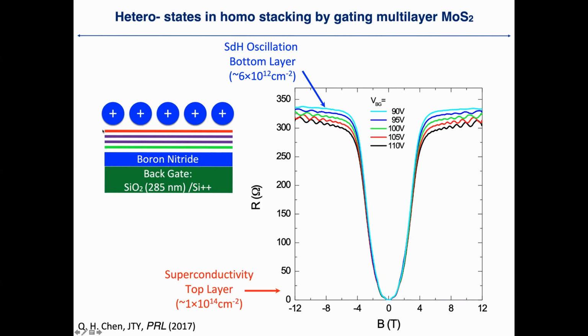And by doing this, we can drive the top layer into a superconducting state, and as we can see, by applying a magnetic field we can suppress the superconducting state. But then at high magnetic field, we start to see some oscillation, right? Then this oscillation scales by applying a larger gate voltage from the back. And if you analyze the oscillation period of this feature, you realize that it's coming from a carrier density of 6 times 10^12, which well agrees with the silicon dioxide solid gate. But on the other hand, if you drive the superconductivity, this top layer should be on the scale of 10^14. So by doing this, we can separate the electronic structures very well.